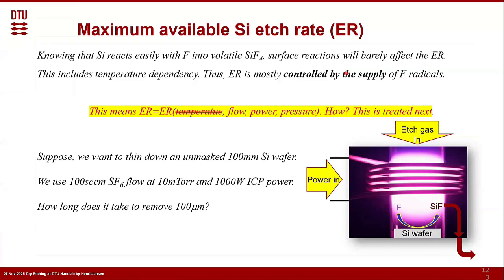So we know that silicon reacts. We just saw it very easily with fluorine into this volatile silicon tetrafluoride. And in a way, surface reactions, because of that, barely have an effect on the etch rate. It means that the etch rate is in fact controlled only by the supply of fluorine radicals. So when they are coming to the surface, they will do that job. But it is how many are arriving. So we have to look at it in the way that we have to supply them, and it will be depending on the flow.